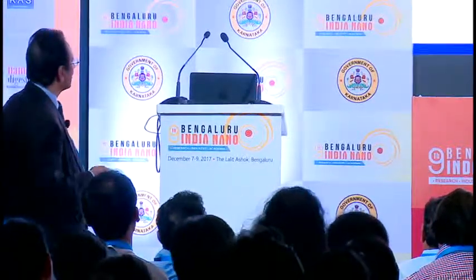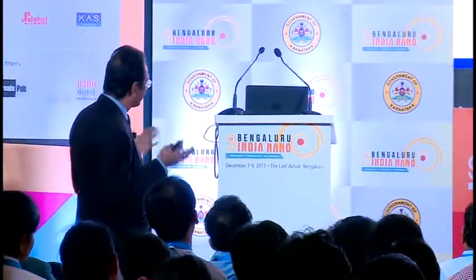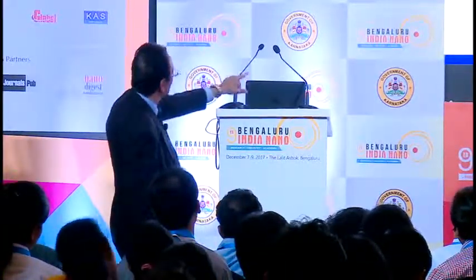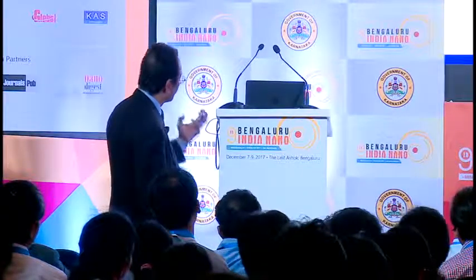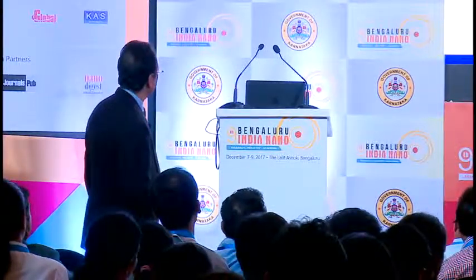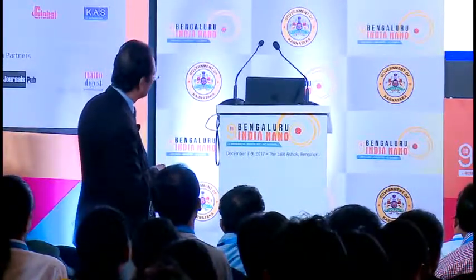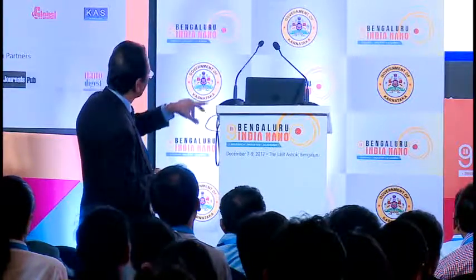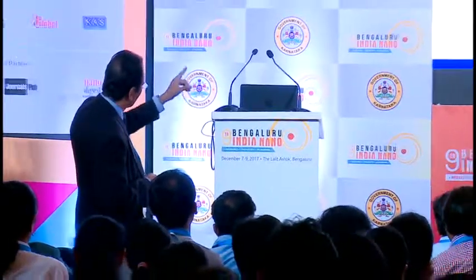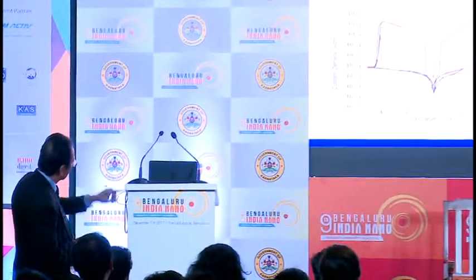So essentially, you can study this using Raman spectroscopy. And again, this is the first example of an organic device which lends itself so beautifully to understanding the different states of the device. Okay? So you can tell what is the valence state or the redox state of the ligand, and it exactly shows through Raman spectroscopy. Just absolutely stunning. And the hysteresis is obtained because of what's called a counter-ion, which is used to balance the charge of the ruthenium. And if I make the counter-ion sluggish, like chlorine, which is a light counter-ion, I get a very broad hysteresis. PF6 is a little bit heavier, you get narrower. When I go to the BPh4, which is a much heavier counter-ion, it becomes a much narrower hysteresis.